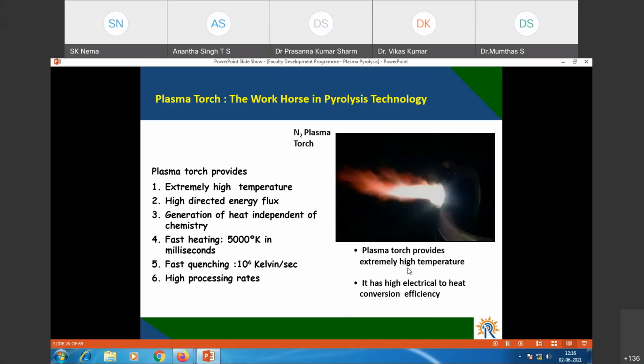This torch provides extremely high temperature. Its conversion efficiencies, like electrical to heat conversion efficiency, are very high, more than 90%. These are certain characteristics: high directed energy flux, and generation of heat independent of chemistry. You don't require air or other things for burning of the fuel, like in conventional burners, where the fuel requires air or oxygen. But here, in any gas you can generate plasma, in nitrogen or